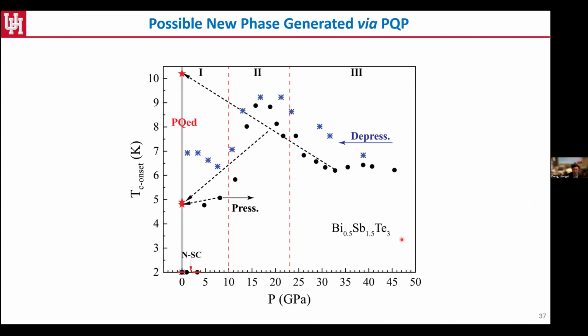Another exciting thing I want to point out is something that unexpectedly happened. When we're talking about the pressure quenching phase, the ideal case, the nicest case, would be that we retain a TC as high as we created under pressure. But what happened is even better. When we pressure quench in this phase, we got a TC that was higher than any of the TC created under pressure. So that basically shows that PQP is not only an approach to catch those high pressure, high TC phases, but also gives a chance to discover some new phase that never existed, either at ambient condition originally or under pressure. So that's a very interesting thing.